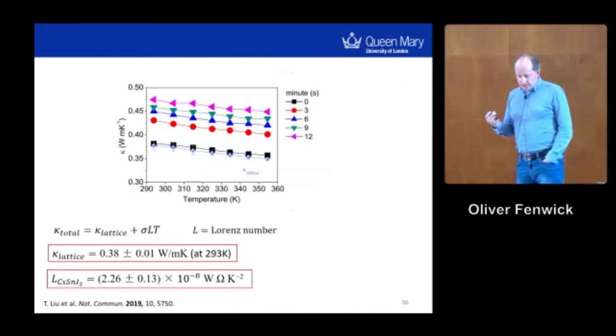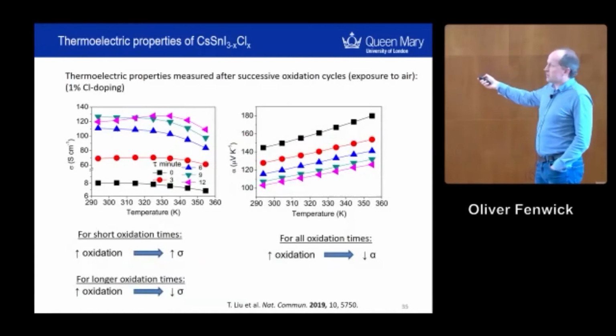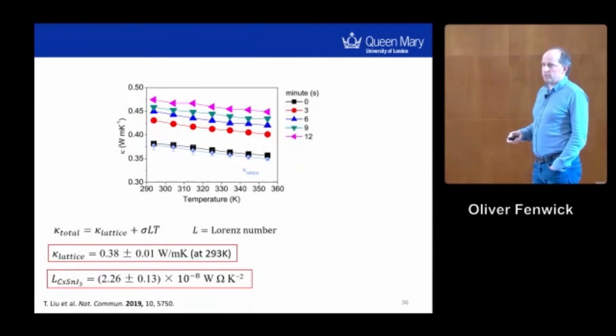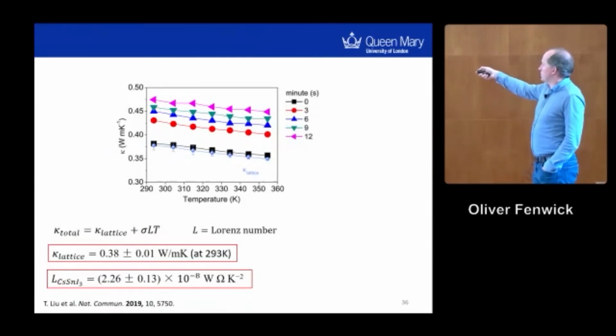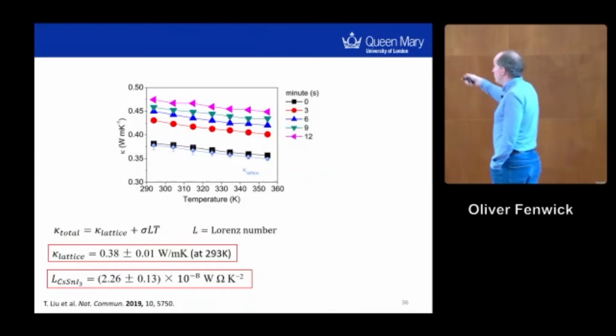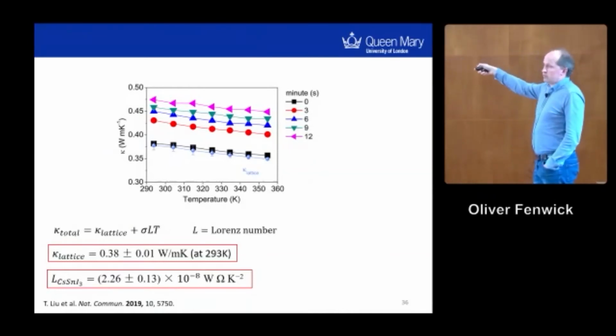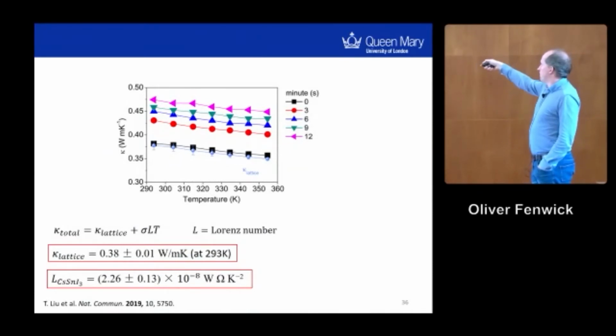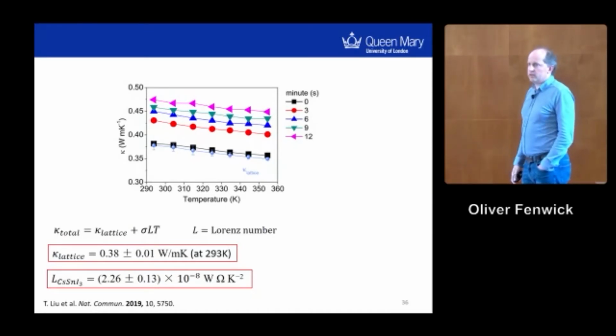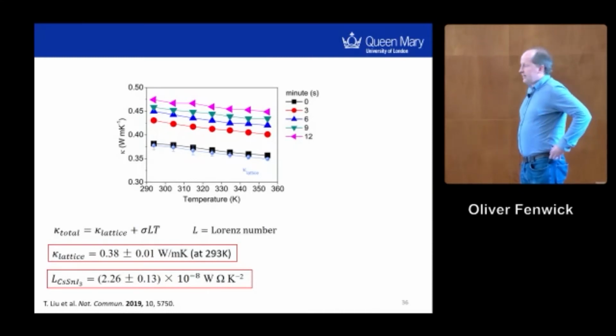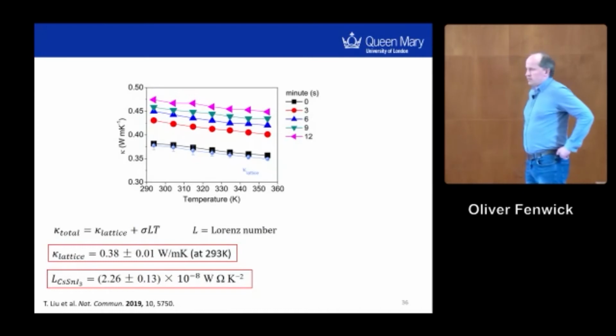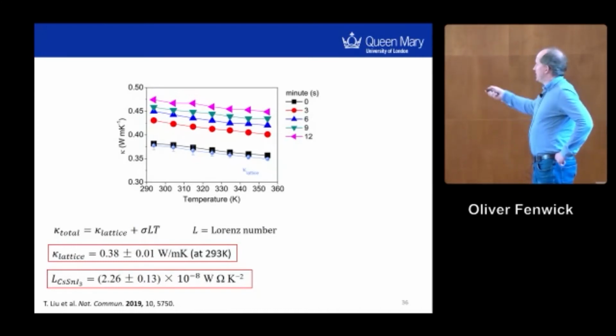The thermal conductivity is interesting, so we get to about 100 Siemens per centimeter. At this electrical conductivity, we can see an electrical component to the thermal conductivity. Our total thermal conductivity is, of course, the sum of the lattice component and the electronic component, which is given by the Wiedemann-Franz law, so it's proportional to the electrical conductivity, the Lorentz number, and the temperature. If we fit our data, we find that the lattice thermal conductivity is about 0.38 watts per meter Kelvin, still very low. And the Lorentz number is this, and that's very close to Sommerfeld's value of the Lorentz number, which is the value you get for a free electron model, and is typically what you get in most of the ceramic thermoelectric materials, or maybe very slightly less. I think it was reassuring that our thermal conductivity measurements were sensitive enough to pick that number out.